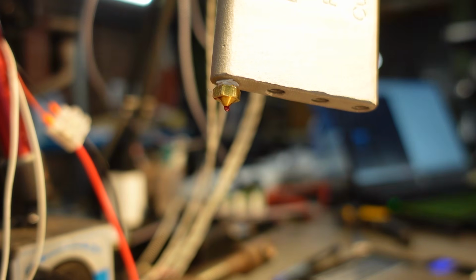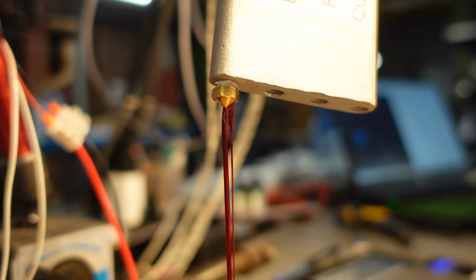But you can now see that there is some serious die swell going on. So I'm guessing the viscosity has changed. The material itself isn't fully melted. I mean, it's able to push it through this 0.8 millimeter nozzle, but there is no mechanism like a CHT or splitting geometry or something that really gets to the core, but it still manages to do that. That doesn't necessarily mean that it's good for a real-world 3D printing application, but I'm just gonna see how much of a graph I can derive from that. So this is again the flushing move. As you can see, this is bigger than 0.8.